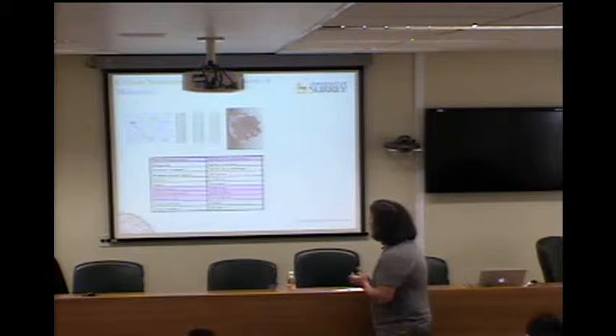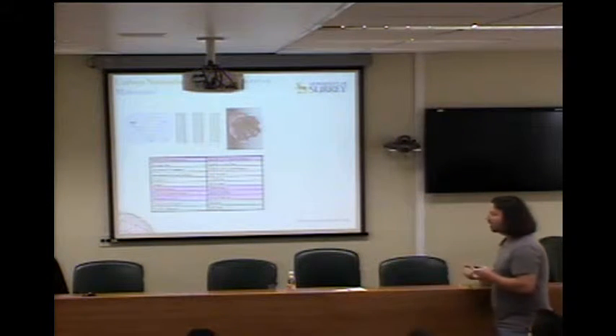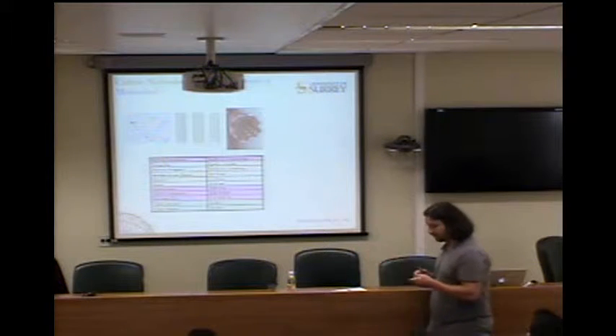Okay, so I'll give you a little bit of detail about some of the work we've done on carbon nanotubes. So carbon nanotubes are a very beautiful material. You take a sheet of graphene and you roll it up into a cylinder, a seamless cylinder. And the properties of the nanotube are dependent on how one rolls the sheet, so the angle we roll it at, which is called the chirality, and also on the diameter of the tube. And if one can control that, one can control the electrical properties, the thermal properties, and the mechanical properties.